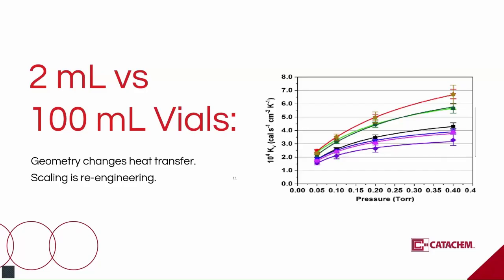If you run a 2 ml cycle on a 100 ml vial without redesign, you invite incomplete primary drying in the lower region, hot spots near the surface as you compensate with temperature, non-uniform residual moisture, and collapse or melt back risks during transients. So scaling by container size requires re-engineering, shallower fills, adjusted shelf steps, and a pressure strategy aligned with the increased load. This slide shows the different energy profiles, i.e. heat and pressure, that relate to successful lyophilization as vials get larger.